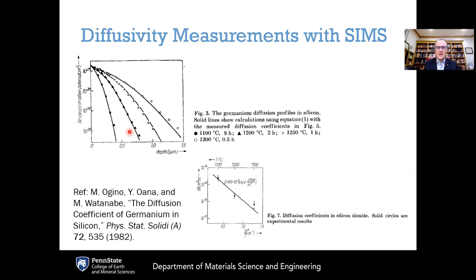This is an example of some concentration profile measurements using SIMS that can be used to get the diffusion coefficient. This shows the concentration profile of germanium as a function of depth into the sample, fitting this to solutions of the diffusion equation from chapter 4, the next chapter. We can get the diffusion coefficient here versus 1 over the temperature. Plotting that gives us a straight line, and then the slope is used to deduce this equation for the temperature dependence of the diffusion coefficient of germanium.